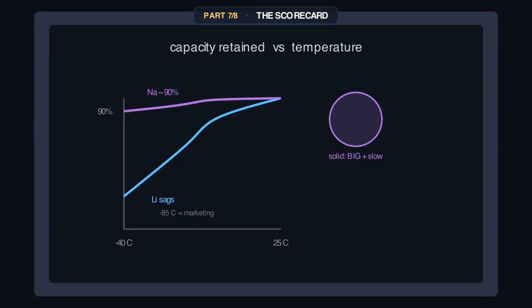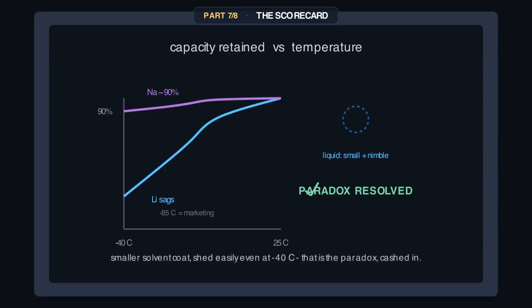But why, when sodium's ion is the big, clumsy one? Here it is. Out in the electrolyte, sodium wears a smaller, looser solvent coat and sheds it easily, even at minus 40, while lithium grips a bigger coat that's brutal to peel in the cold. Big and slow in the rock, small and nimble in the river. Both were true all along.